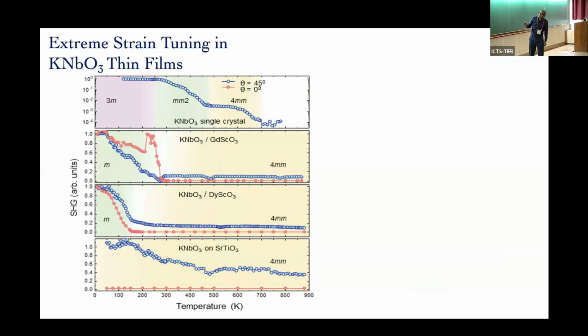We did the second harmonic stuff I just talked about. It's a good way, as I told you, to measure different phases. This is bulk crystal. It has the R, O, T, C. See the 4 transitions. In this case, the 3 films. This one, lowest strain, it's tetragonal mostly and becomes monoclinic at low temperatures, pushes it further by strontium titanate, which is about 1.5–2%.